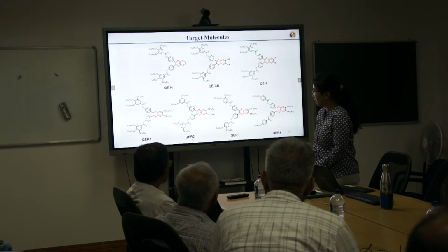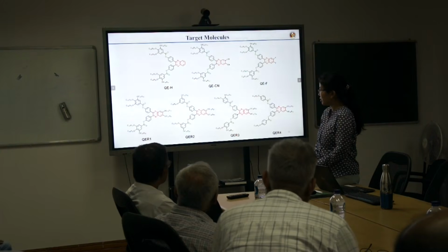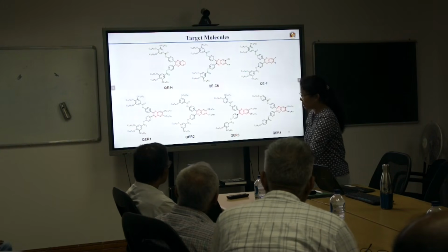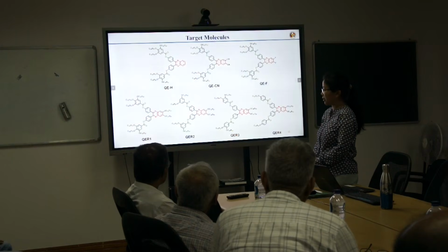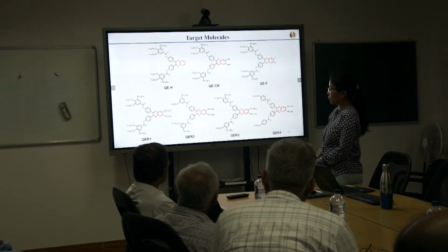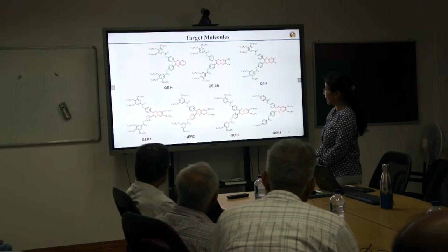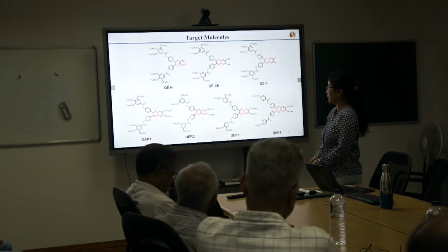So which property? Yes, sir. Actually, only the QER1 molecule was found to be liquid crystalline, whereas QER2, 3, and 4 did not show liquid crystallinity. QER3 was found to be glassy, and QER2 and 4 were found to be crystalline.